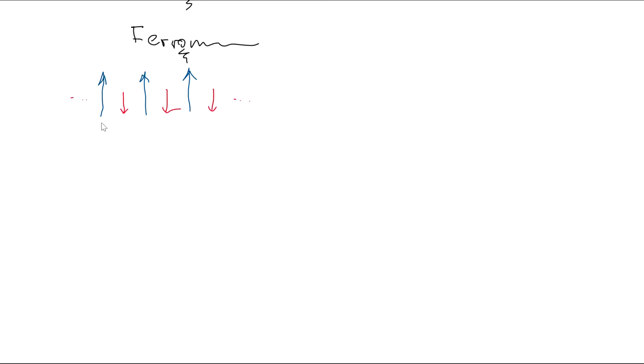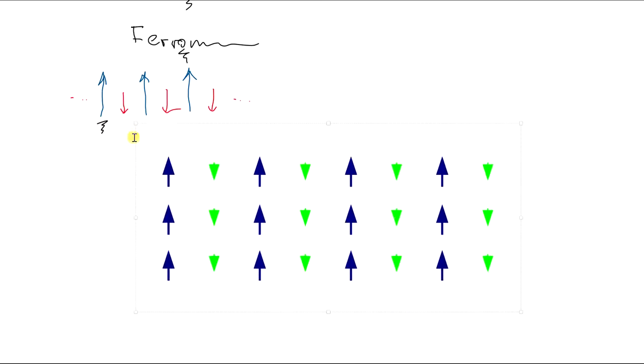As you noticed, this magnetic moment has a big arrow, which indicates a large magnetic moment, and this one is smaller, which means that one of them is bigger and the other one is smaller. When this material is ordered, one of the sublattices has a larger magnetic moment, and this material exhibits properties very similar to ferromagnets. This is a two-dimensional picture, an image from Wikipedia, a non-credible source, but you can see the alignment. There is a ferromagnetic alignment within lattice A, and antiferromagnetic alignment between lattices A and B, which alternate.